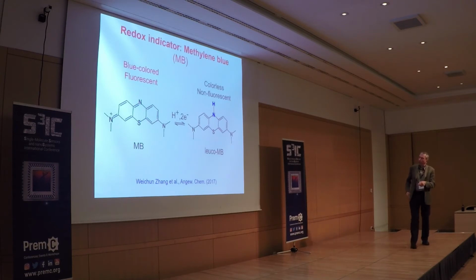You can see here, this is the reduced form. Here it is protonated, it has a hydrogen on the nitrogen. This breaks the conjugation, so this is colorless, does not absorb, does not fluoresce, invisible at least. And when you oxidize, you remove this hydrogen, and you get this conjugated form of methylene blue, which is blue, but does not fluoresce very well. The quantum yield of fluorescence is a few percent, so this is not enough to see single molecules under normal conditions. You have to do something extra.